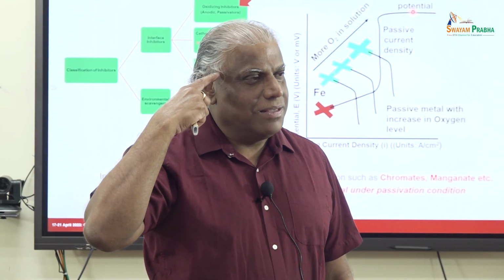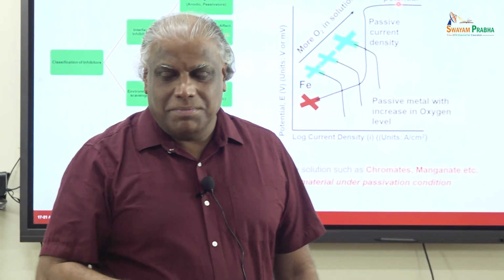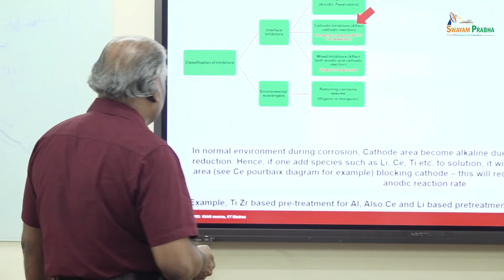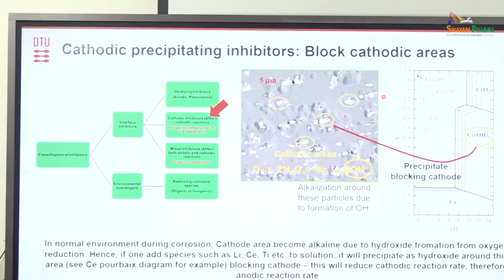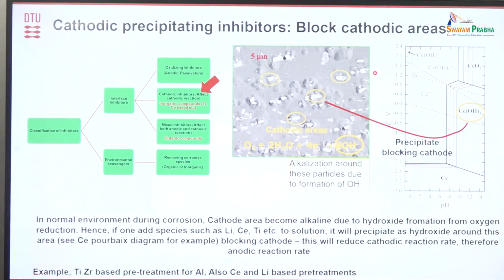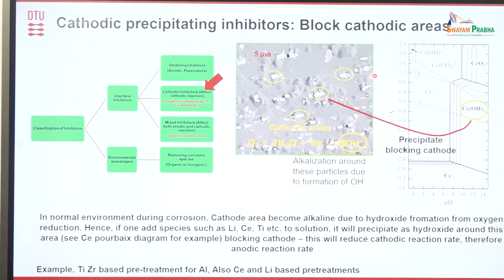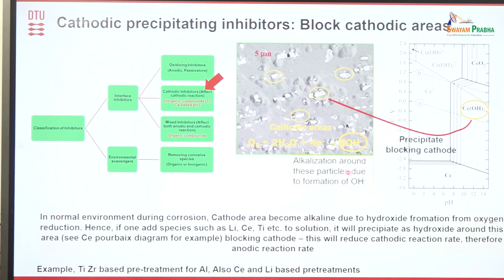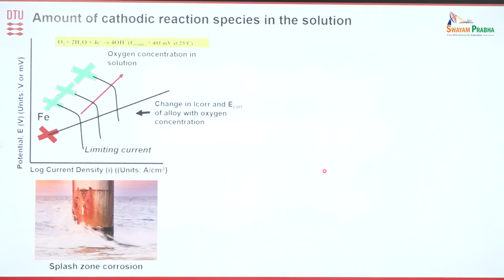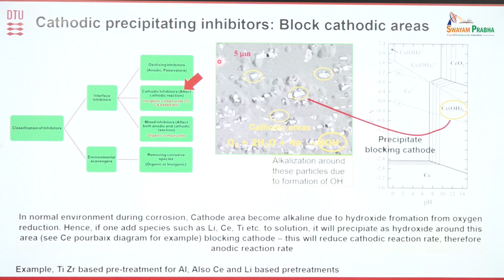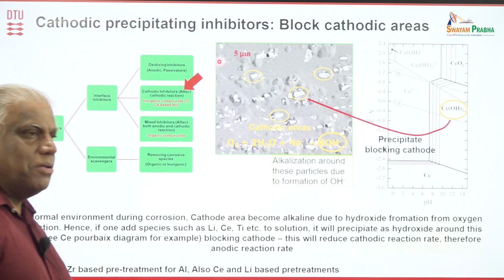It happened actually in wind turbines and things like that, and many of these have failed in that case. Cathode inhibitors basically work with the precipitation mechanism, which I mentioned also, because it is also used as a conversion coating. A typical example is cerium, and in cathode inhibitors we mainly make use of the cathode reaction. Again, this oxygen-based cathode reaction is an important thing, which I am mentioning here, right? This cathode reaction is important because it produces OH minus ions as a byproduct, right? Since OH minus ions are produced as a byproduct, we could use that for many things to inhibit the corrosion. When the OH minus ions are produced, what happens to the pH?